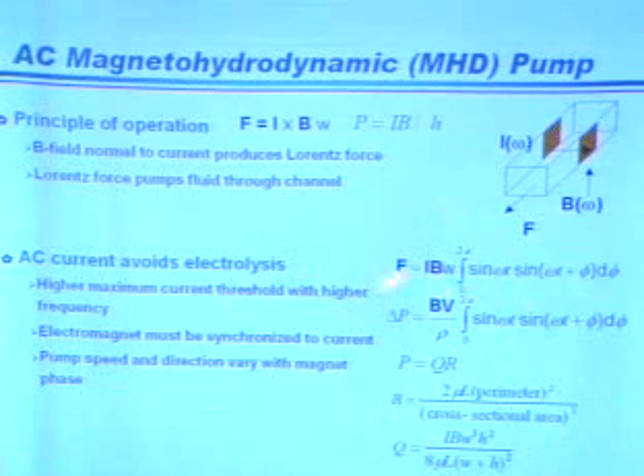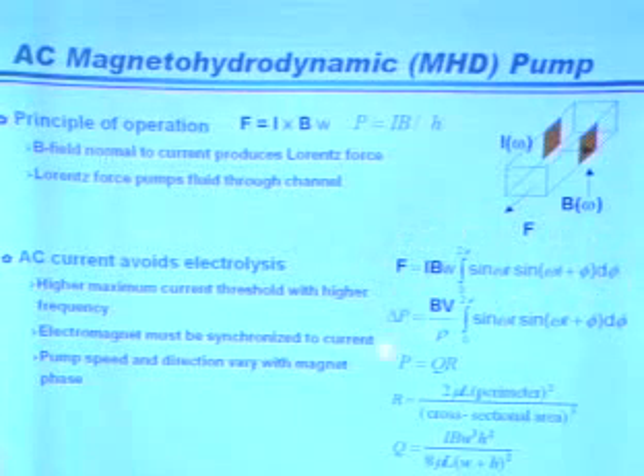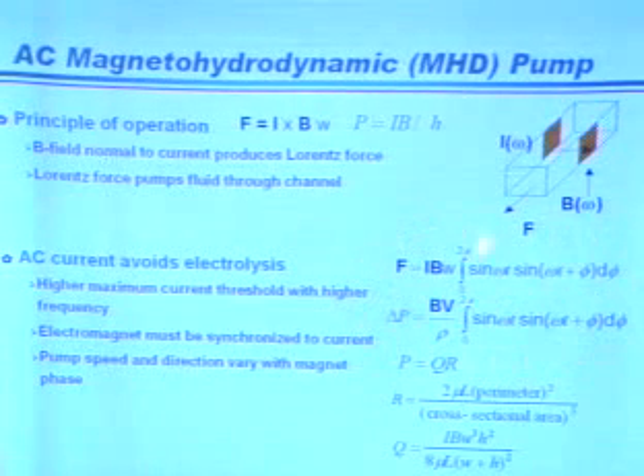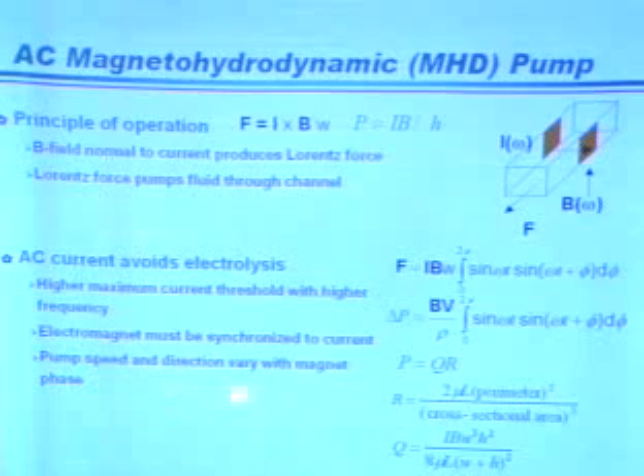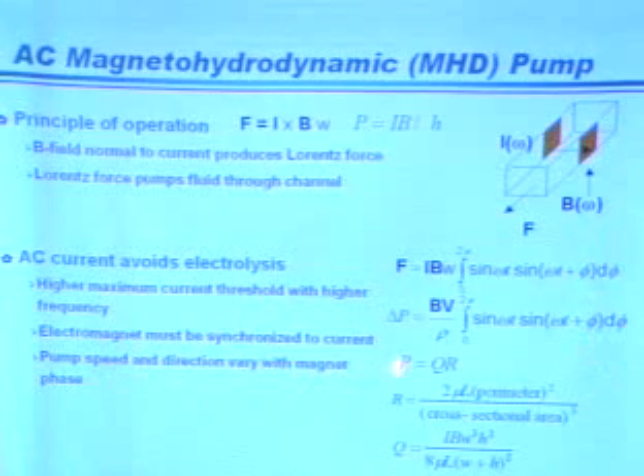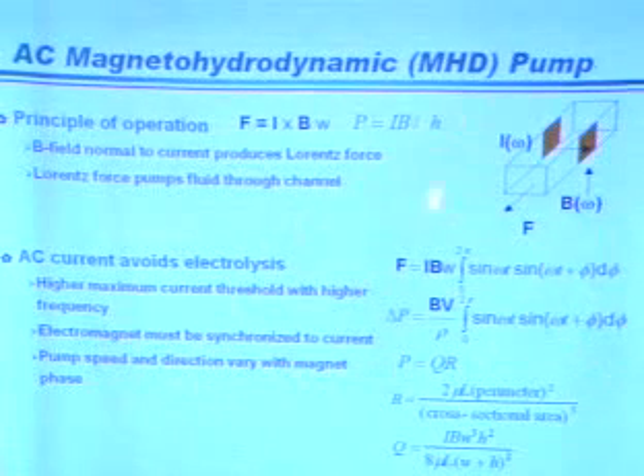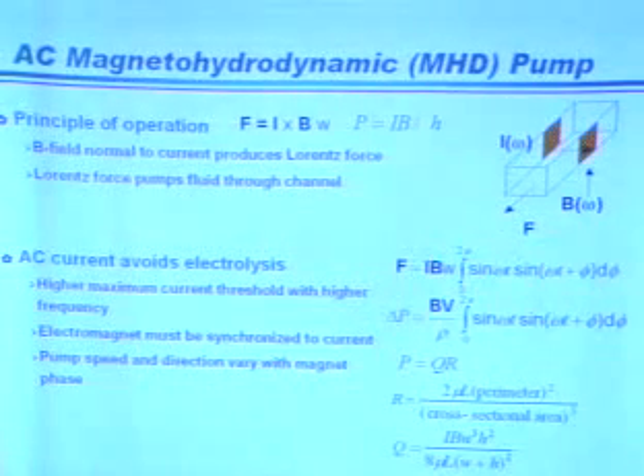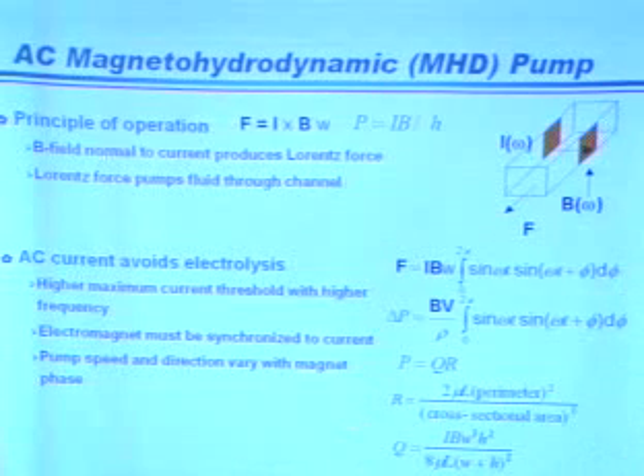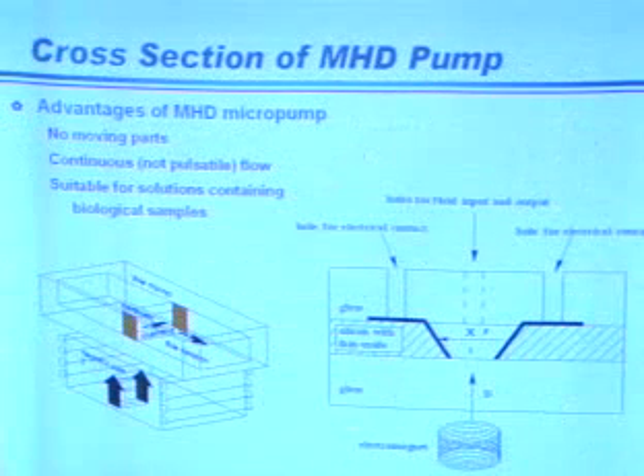But this shows the forces that you can generate, resulting in a pressure that's driven inside the channel. If you look at this formula, there is a phase in there between the two fields. If you adjust the phase, you can adjust the magnitude of your pumping force, but you can also adjust the amplitude of the electrical or magnetic field, and that sets the flow rate.